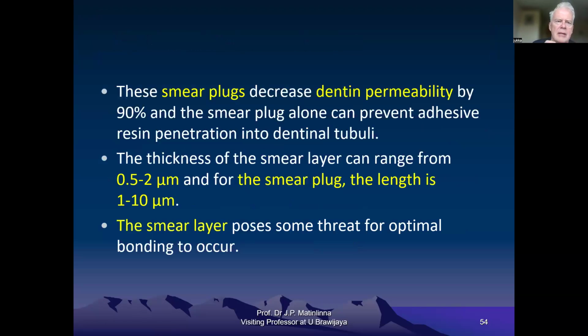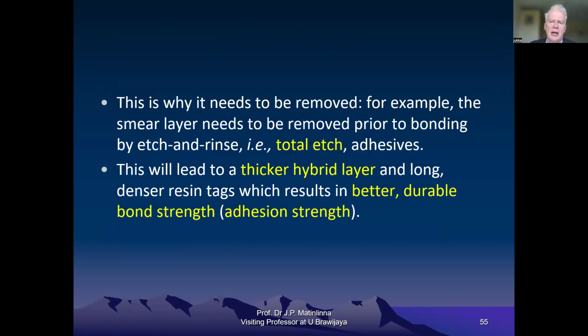This is how we understand it. These smear plugs decrease dentin permeability by 90%, and the smear plug alone can prevent adhesive resin penetration into dentinal tubuli. The thickness of the smear layer can range from 0.5 to 2 micrometers, and for the smear plug, the length is 1 to 10 micrometers. The smear layer poses some threat for optimal bonding to take place, and this is why it needs to be removed.